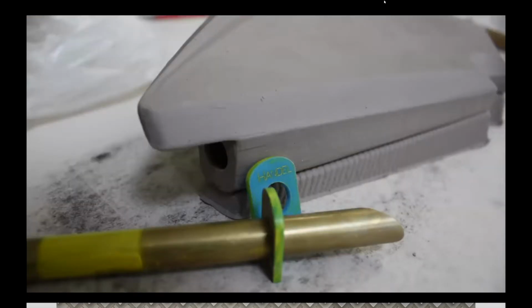Here you can see a close-up of the connection, that portion that's hollowed out. If it was ram pressed, there would be a post-processing step where we would tool that out to receive the mechanical connections. You can also see the more ribbed geometry on the bottom, which was created to support this module as it dries and goes through the kiln, to make sure that it's taking on the true form that we designed through the firing process. Next.